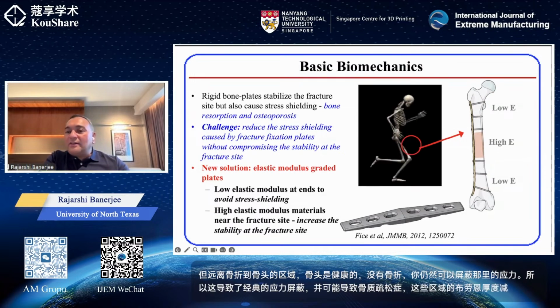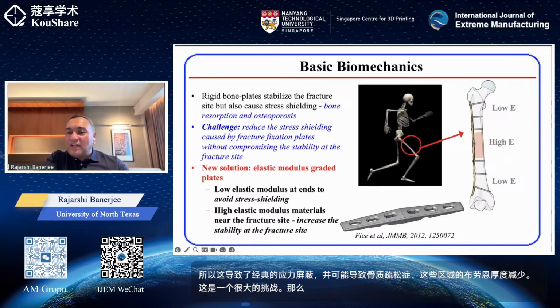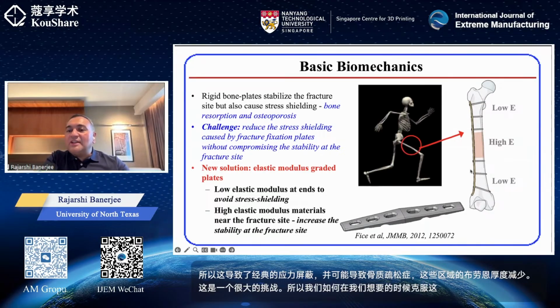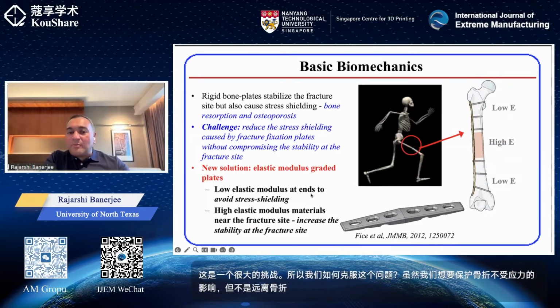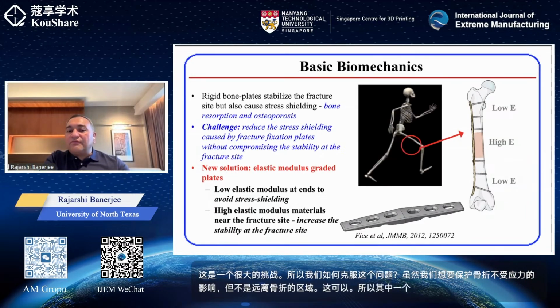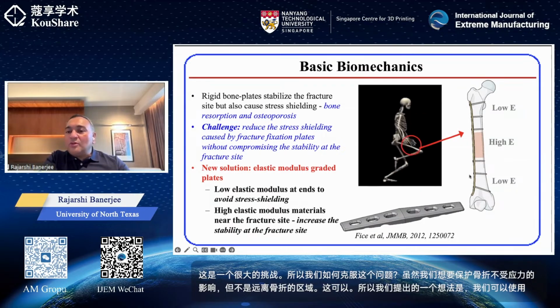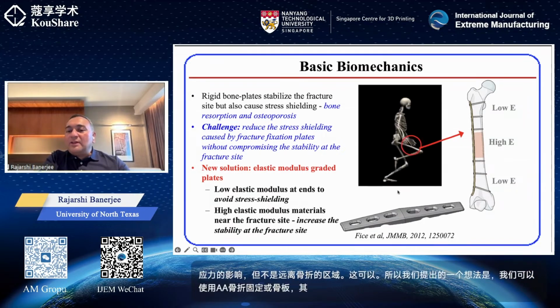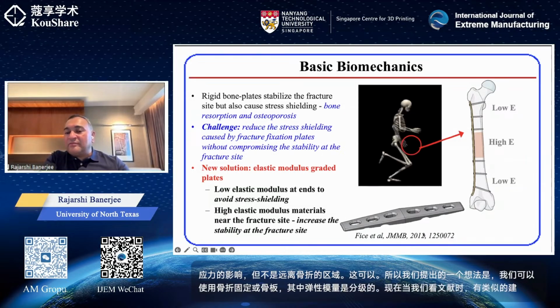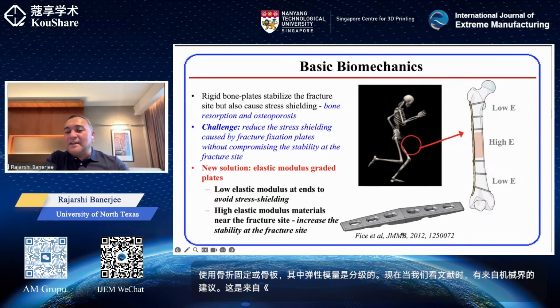So how do we get over this, where we want to shield the fracture from stresses, but not the regions away from the fracture? One of the ideas we proposed is, can we use a fracture fixation or bone plate where the elastic modulus is graded? Now, when we looked at the literature, there were suggestions like that from the mechanics community. This is from the Journal of the Mechanical Behavior of Biomedical Materials back in 2012. They suggested having a thicker section near the fracture and thinner.